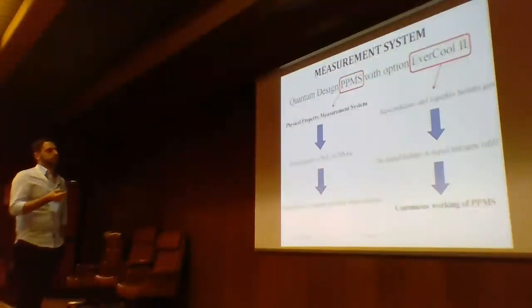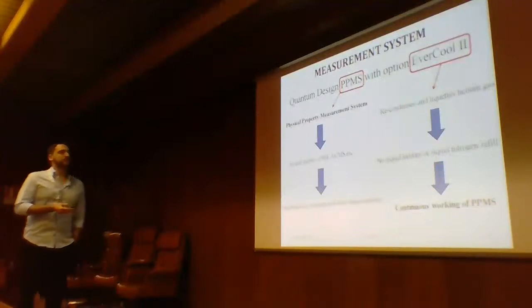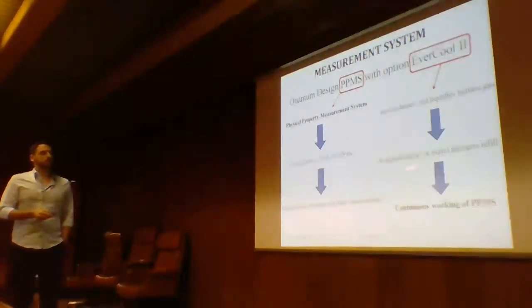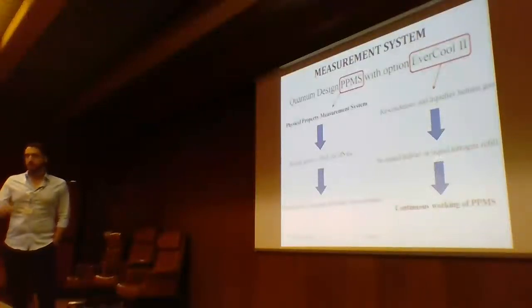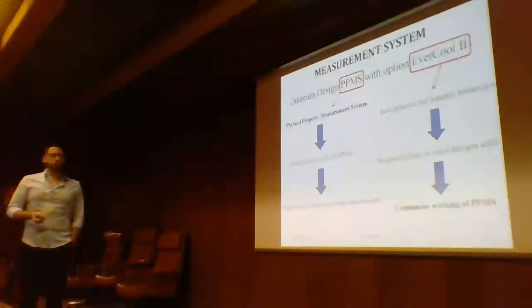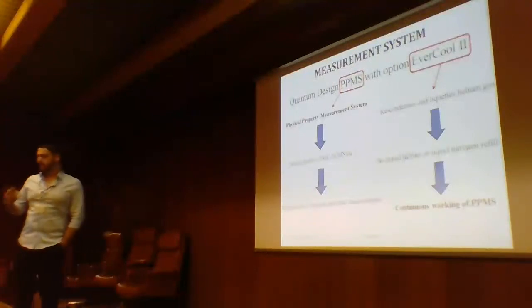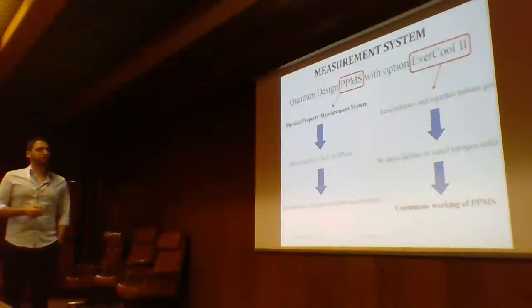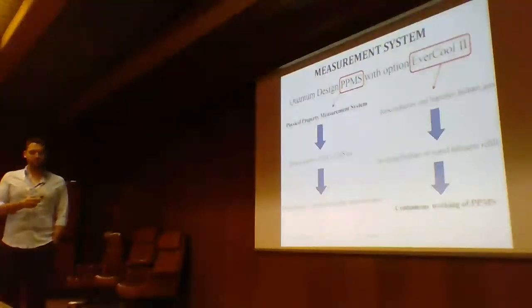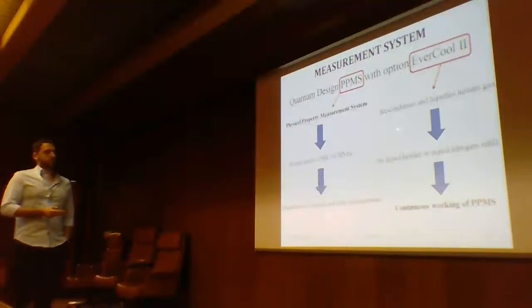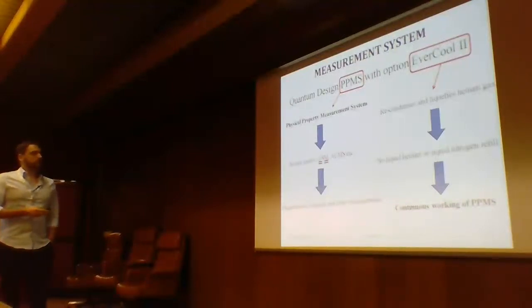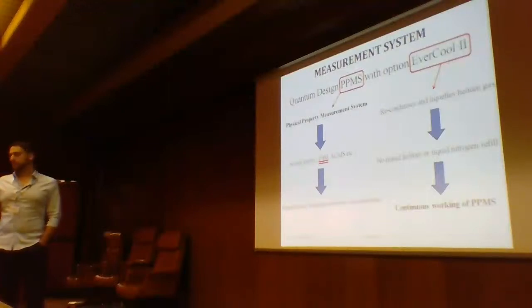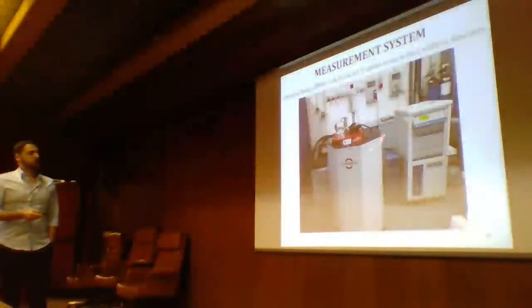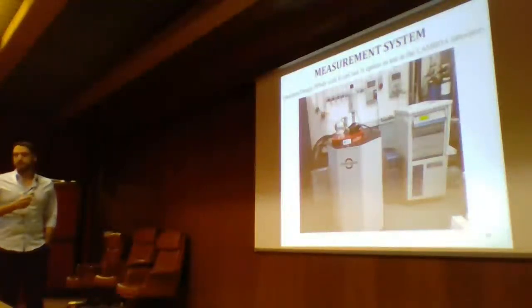Another very important characteristic of this PPMS is this option, EverCool II. Why is this important? Because we can recondense and liquefy helium gas, so there is no need to refill your system with liquid helium and liquid nitrogen, and this means that you can use your PPMS continuously. This is very important because, as you know, liquid helium is very expensive, and to obtain hundreds of liters of liquid helium is very difficult for our funding. So this option is very important. We will study in particular measurements performed with the vibrating sample magnetometer, so in DC magnetic field. This is a picture of the PPMS used at the Lambda laboratory in Salerno.